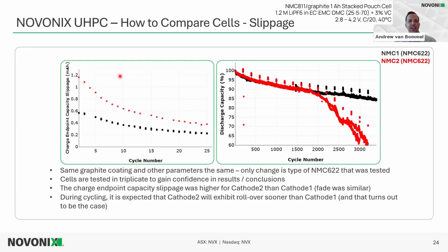And then looking at slippage. In these two cells, these are two NMC 622 chemistries. So the red, I'm saying it's NMC 2, the black NMC 1. In this case, the discharge capacity fade was similar for both materials, both the cells made with both materials. You can really see that during long-term testing. It's almost the exact same fade. But we do see that the charge endpoint capacity slippage is higher for this red NMC 622 than for the black one. So this would suggest this will probably roll over quicker than the black one, due to some of those reasons that I mentioned before.